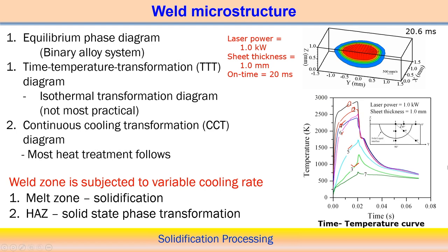And if you see, the cooling rate is also different at the different positions 1, 2, 3, 4, 5, 6. So we can expect different microstructures to form, depending upon the rate of cooling during the welding process. This kind of information is useful to estimate the cooling rate at one particular position, and that is why we are discussing the heat flow analysis associated with the welding process. Based on the cooling rate we can predict the microstructure. So we will try to link the rate of cooling with other aspects of solidification, and what can be the final microstructure for the different materials in a fusion welding process.